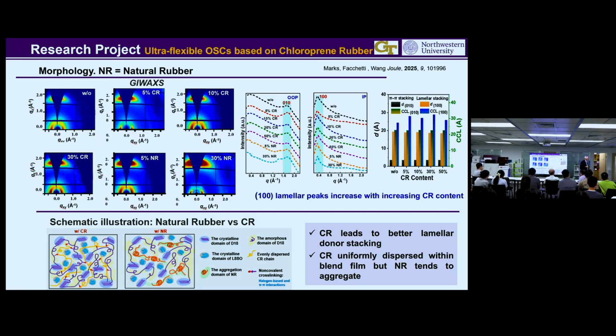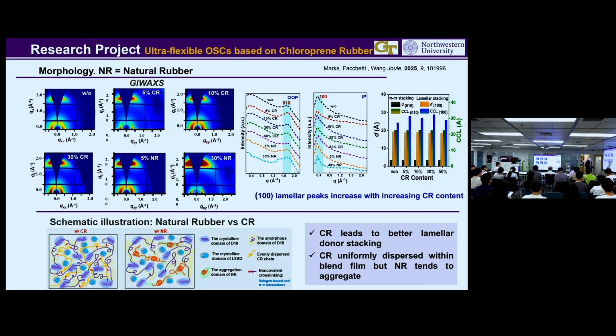When I add more and more chloroprene, this shows that, and then this is the stacking between the pi systems and the separation between the stacked pi systems. You see that adding the chloroprene does not have such a dramatic effect. Maybe the chains spread apart, but the stacking stays the same.